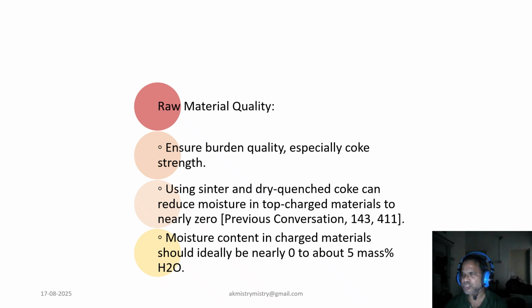We must ensure overall burden quality, especially coke strength. Using sinter and dry quench coke can reduce moisture in top charge material to nearly zero. Ideally, moisture content in charge material should be almost 0 to about 5 mass percent H2O.